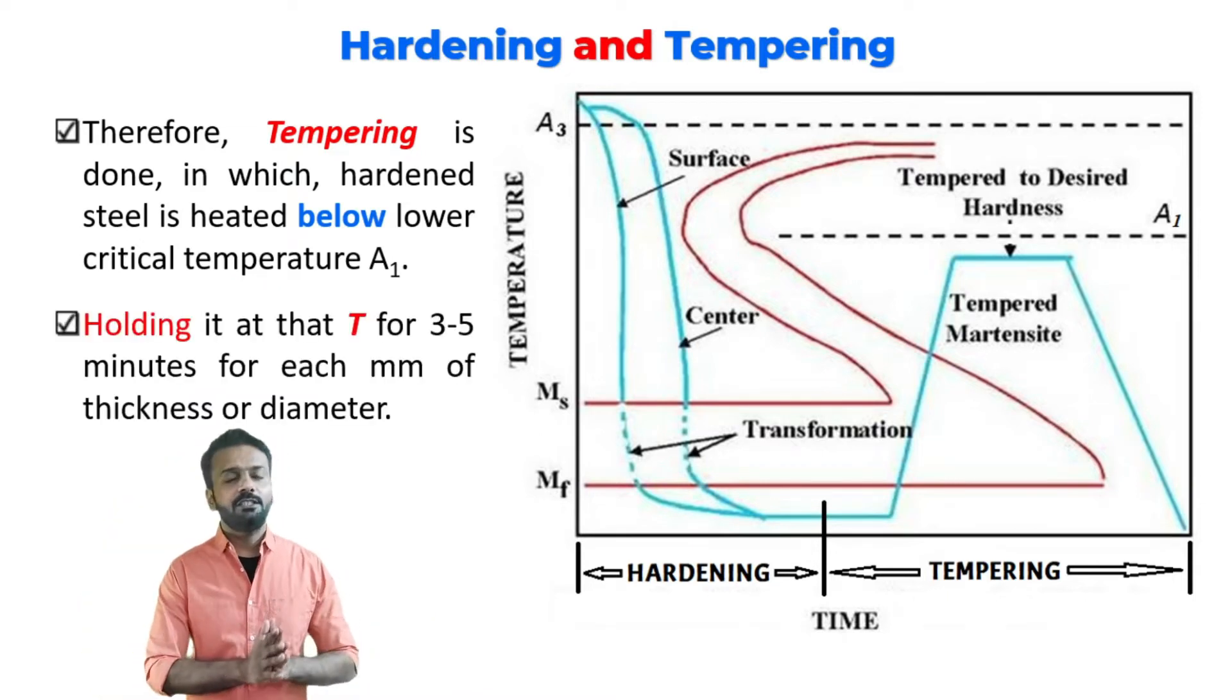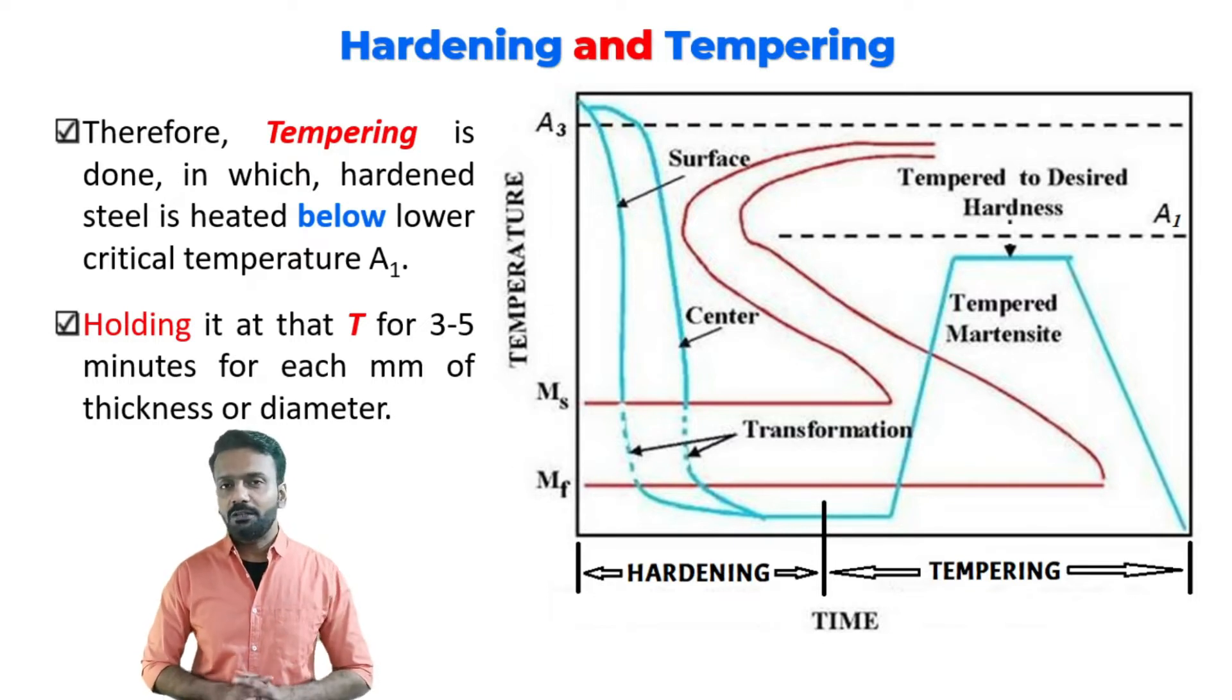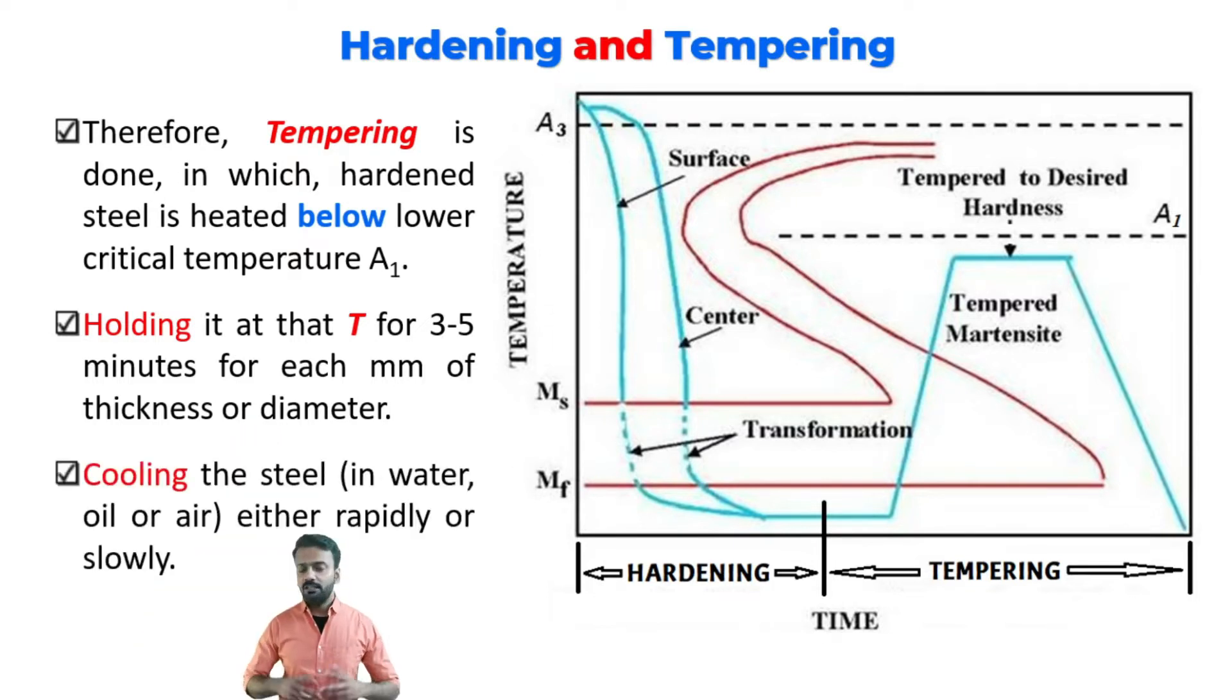Holding is done based on a thumb rule: 3 to 5 minutes per millimeter of material. Cooling is done either in air, oil, or water - that is your choice, because after holding the material, the purpose of tempering is achieved and we have eliminated the brittleness.